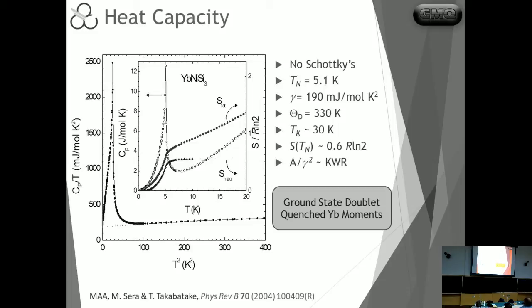So it seems like this is very much, although it is a hybridized Kondo lattice, a system that still has very strong RKKY connections between the ions. You see that the gamma shows somewhat enhancements, right? So we have a moderate heavy fermion system here. This gives us a Kondo temperature of around 30 Kelvin.